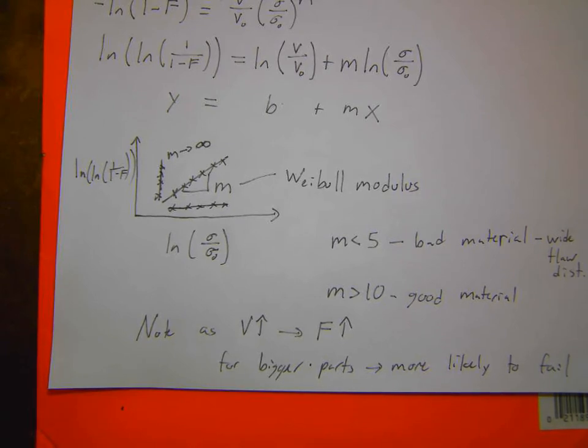So there's one other interesting application for this. Because the failure of a material is dependent on the volume of the parts, it also works the other way, where if you have smaller parts, they're less likely to fail. So that works at any scale. If you have say some carbon fiber, silicon nitride fiber, or whatever, and you reduce the diameter, it's going to be statistically stronger. And so the smaller you can make those fibers, the stronger generally they're going to be.